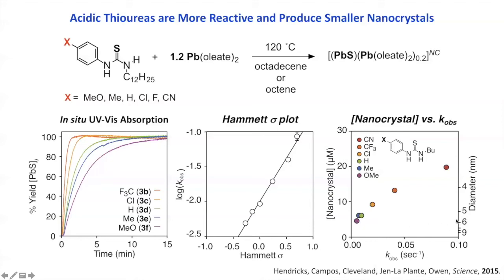So we verified in these kinds of conditions that the conversion reaction rate constant to the precursor is related to the final size of the crystal at the end of the synthesis. Some of you might be wondering, what about Ostwald ripening? Ostwald ripening would mar this result, or maybe obscure or flatten this curve. And it turns out under these conditions, the solubility is so low that the crystals don't exchange monomers very rapidly, and the kinetics of Ostwald ripening are too low to be important.